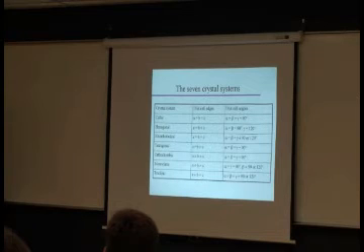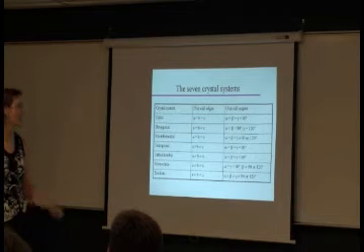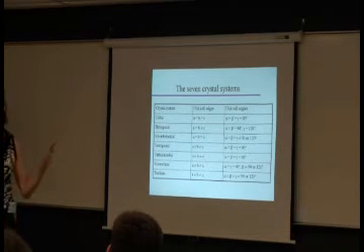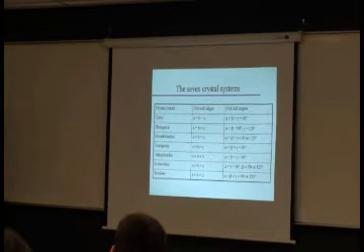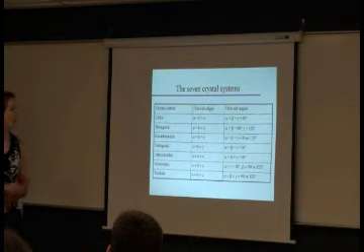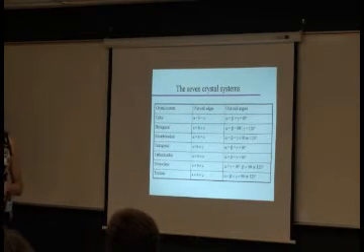Monoclinic, usually you choose beta to not be equal to 90 degrees. Okay, that's just convention. So if you read the crystallographic literature, you may actually find something that just tells you lattice constants A, B, and C, and beta is, for example, 95 degrees. They would expect you to recognize that that is a monoclinic crystal. They probably wouldn't even tell you that alpha and gamma are 90 degrees. So in crystallography, unless specified otherwise, the angles are either 90 degrees or in the hexagonal system, 120 degrees. Okay?